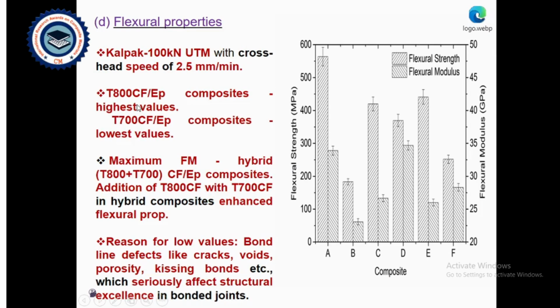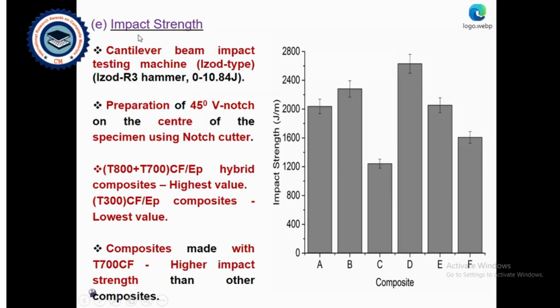Flexural properties. Once again, a crosshead speed of 2.5 mm per minute was used. T800 composites provided the highest value and T700 composites showed the lowest values. Maximum flexural modulus was observed in hybrid T800 plus T700 carbon fiber epoxy composites. Addition of T800 carbon fabric with T700 carbon fabric in hybrid composite enhanced flexural properties. The reason for low values may be bond line defects like cracks, porosity, voids, kissing bonds, etc., which seriously affect structural excellence in bonded joints.